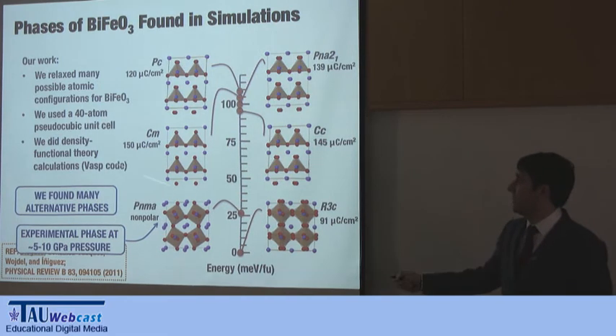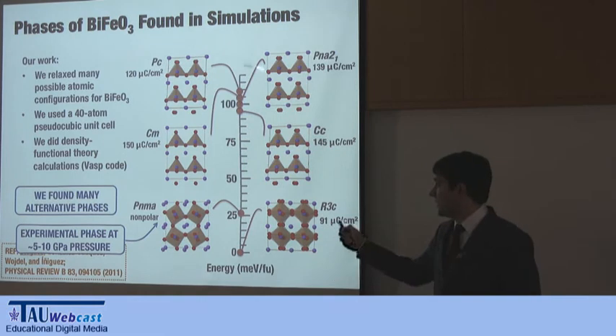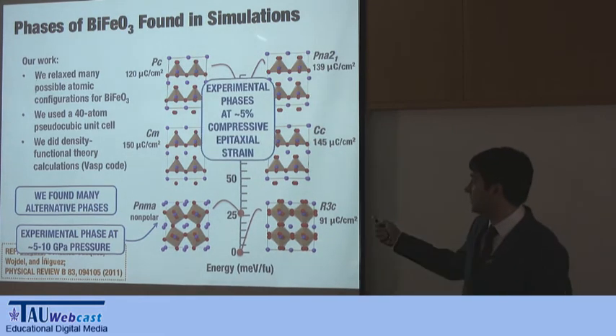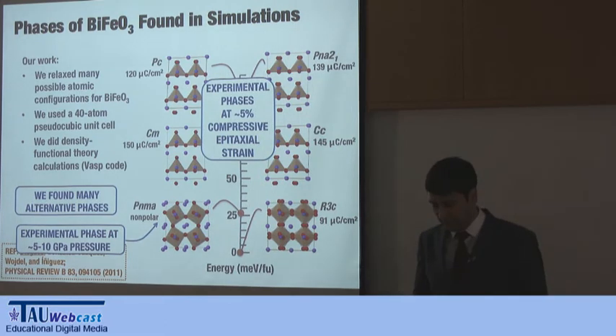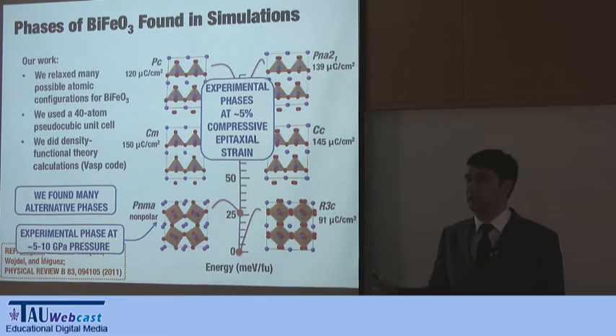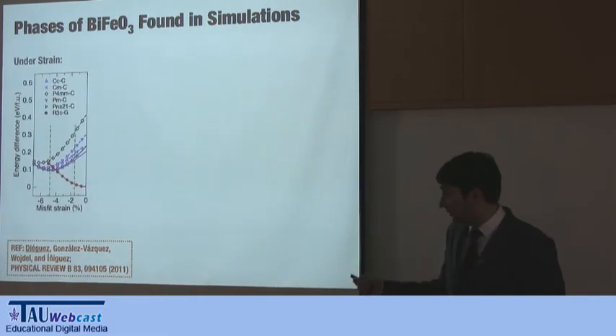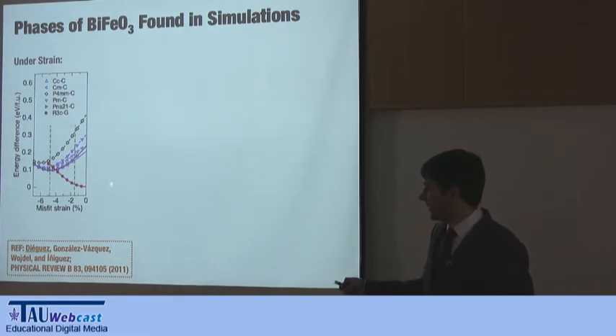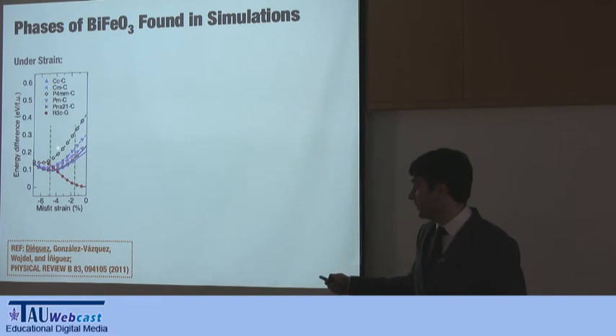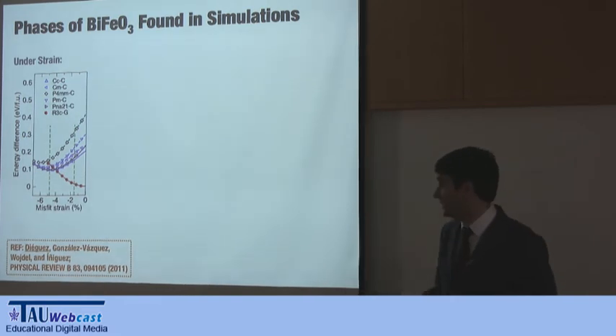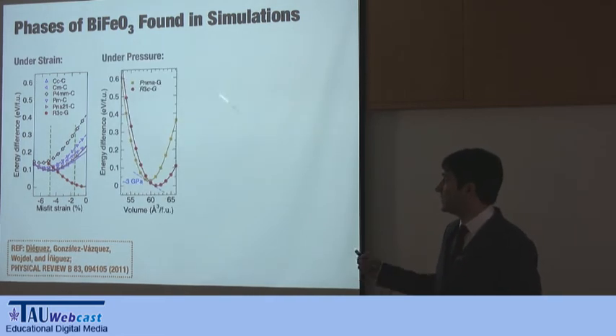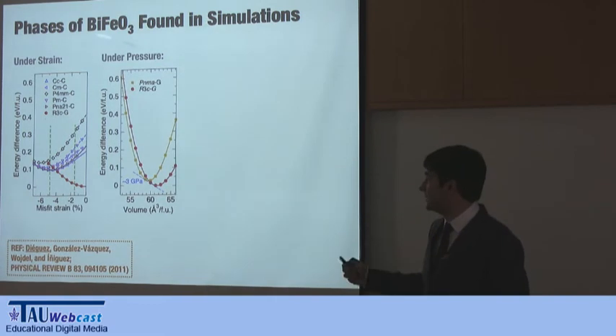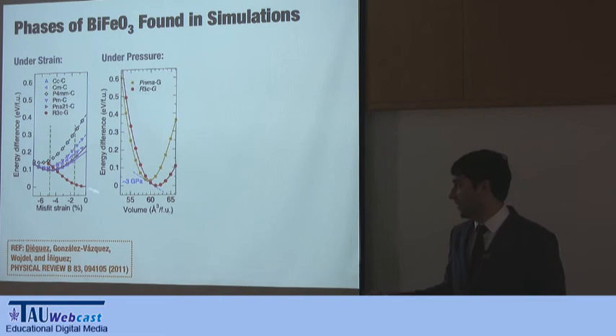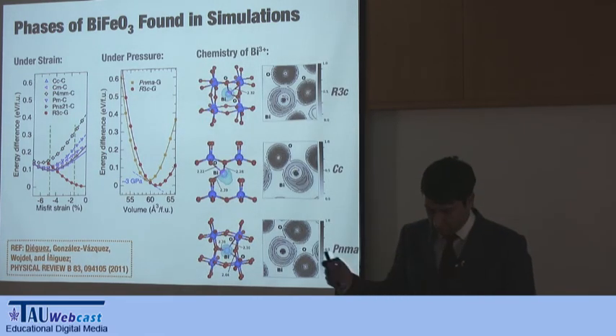So can you stabilize these phases that appear for the solid, is there a way to stabilize them? And yes, there is. And similar phases to this appear in ferroelectric films, if you, again, grow them under strain. So apart from looking at experiments and where they show up, we can find how well we agree with experiments by computing at different strains what happens with the films. We find that they are stable at around 5% of strain, as the experiments show. We can check where the pressure phase transition occurs. We find it's around 3 gigapascals, and again, this is close to the experimental result.